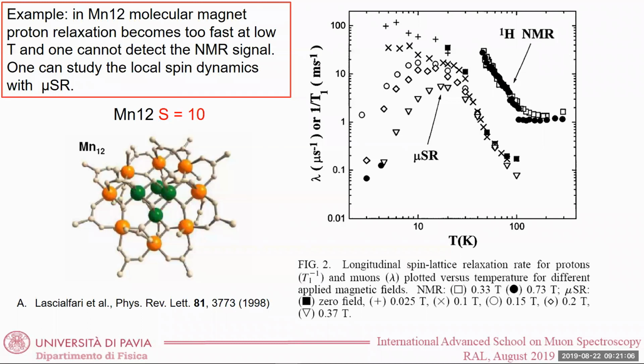And since with MUSR you can access much faster relaxation rates, you can start to do MUSR. And you follow the same trend and you pass through a maximum, which indicates that you have a slowing down of fluctuations which reaches the Larmor frequency. And so in this case, we could study well the temperature dependence of this spin dynamics associated with the slowing down of fluctuations in this molecular magnet.